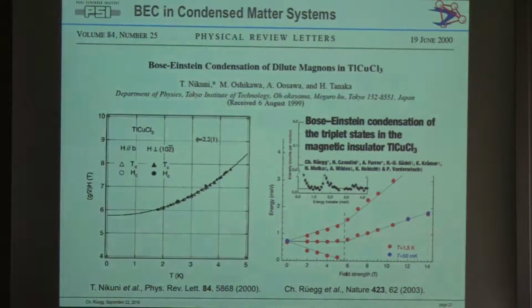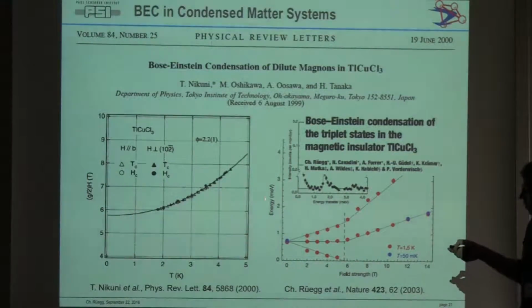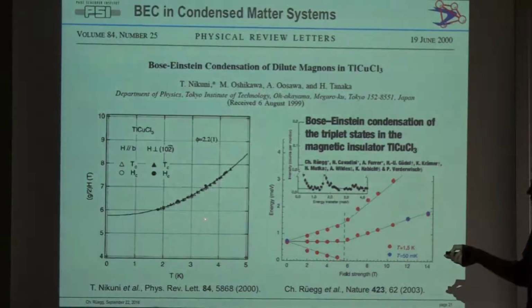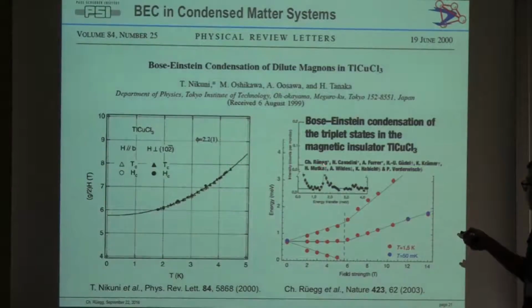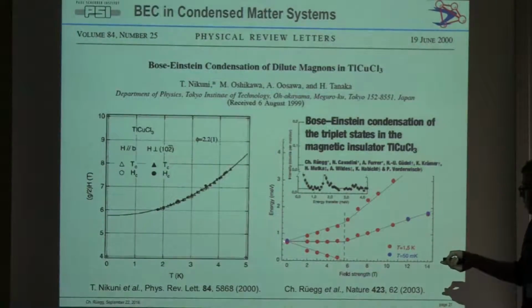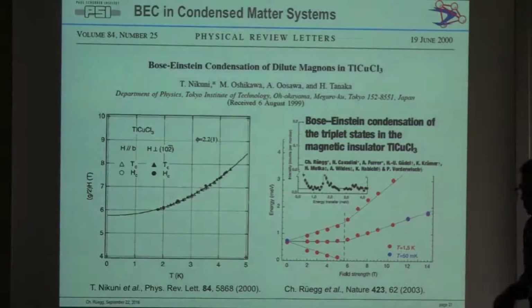A couple of years earlier, we had realized this analogy between the dimer states and BEC, and that was done in Japan first, where people looked at the condensation phenomena itself. So that's a phase transition in these 3D ordered phases. This was measured, critical exponents were extracted, and that was a first indication. Myself, we measured the excitation spectrum. This is just a trivial singlet-triplet splitting, but then in this condensed phase, you get at low energies, which is not shown here, actually the linear dispersion of the excitation we discussed yesterday, and these are the gap modes.